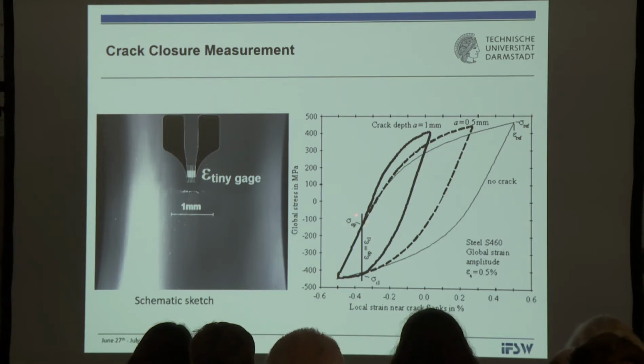And you will be able to identify locations where these loops deviate from one another and where they come together to one loop branch here. We are totally sure that at that position the crack flanks lose contact and they gain this contact again at that position. So we draw a vertical line here, and this line discriminates in these loops those states where the crack flanks are in contact and those states where the crack flanks are no longer in contact. And these are the effective ranges, and we believe that the effective ranges drive the crack further.